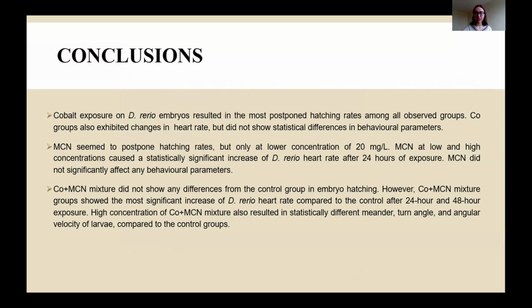And so to conclude, what we observed is that cobalt exposure to Danio embryos resulted in the most postponed hatching rates among all observed groups. Cobalt groups also exhibited changes in heart rate, but did not show statistical differences in behavioral parameters. The MCN seemed to postpone hatching rates, but only at the lower concentration of 20 milligrams per liter. MCN at low and high concentrations caused a statistically significant increase of Danio heart rate after 24 hours of exposure, but not later, and it also did not significantly affect any behavioral parameters, as we saw.